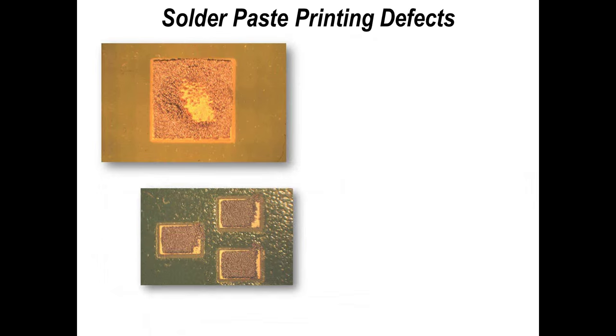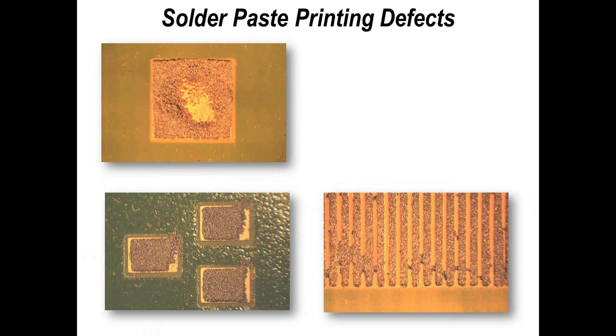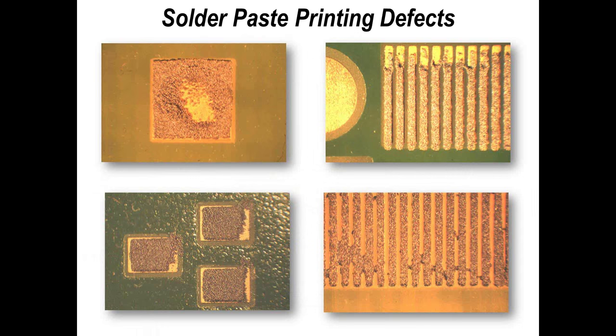Now, printing defects, well, we've been trying to deal with these for many, many years, and here are some relatively simple ones. So on top left, we've got scooping, and this is where solder paste is printed onto a pad, but the pad is larger than we can effectively print. And the reason being, with a metal blade, certainly far more obvious with a rubber blade, we're scooping solder paste out of the aperture, possibly due to the pressure we're applying or possibly just to the size. So wherever you've got larger apertures, you want to break them up into segments.